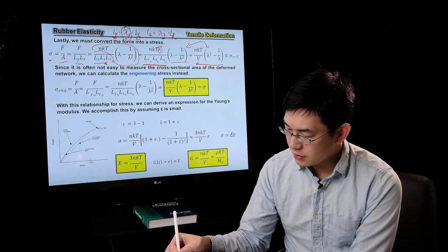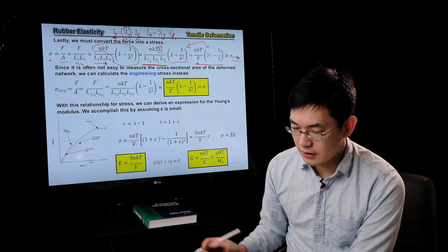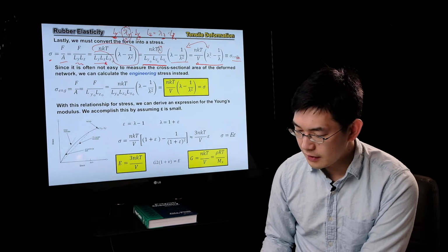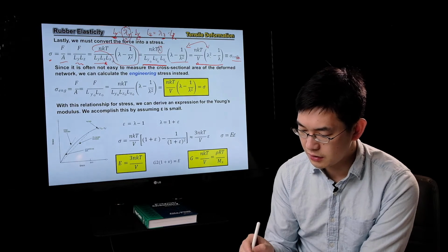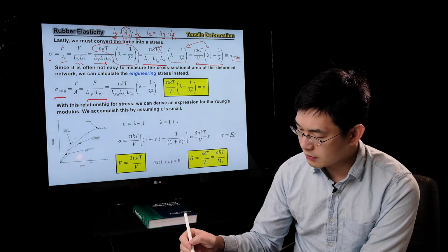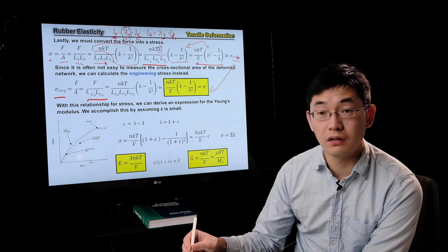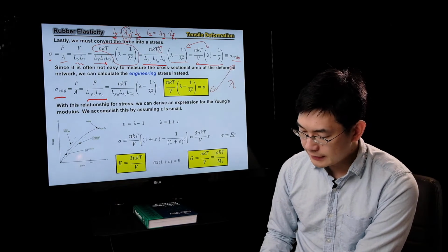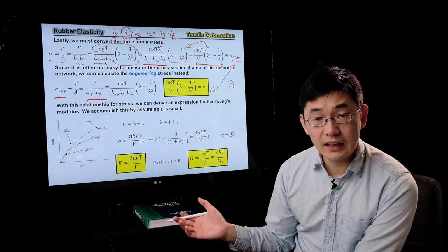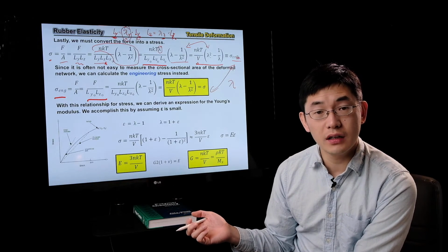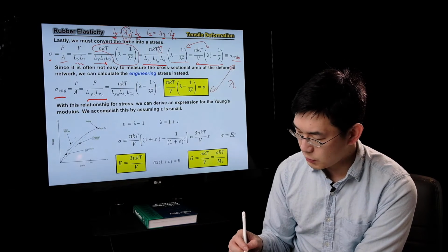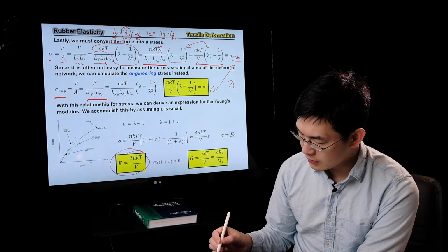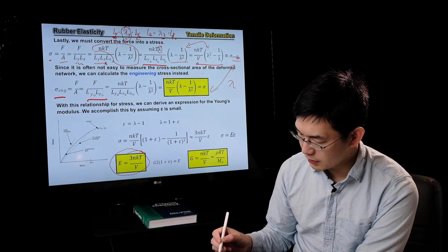This is defined as the true stress in a material system, so how the true stress depends on the value. And you could also have engineering stress, where you divide by the initial value. So engineering and true stress, as we know, should only differ by a factor of lambda, which is the case right here, okay? We can also link your stress and strain to get the Young's modulus. Young's modulus is defined with this particular equation, and you can also get the other values related to them.